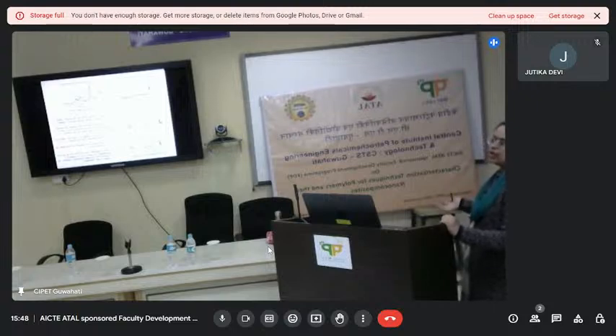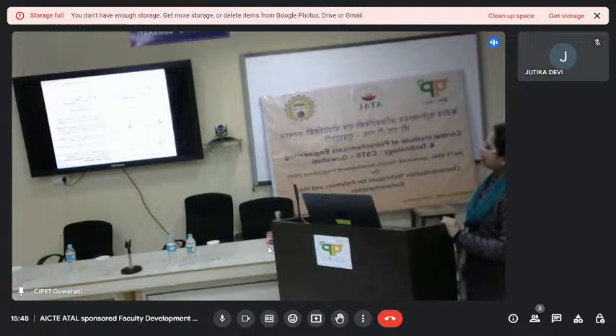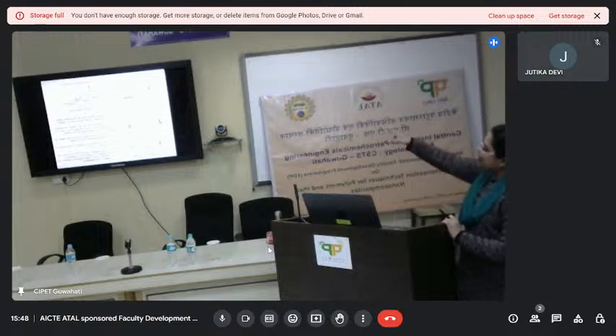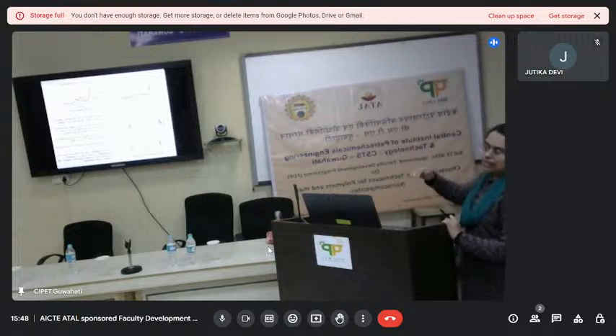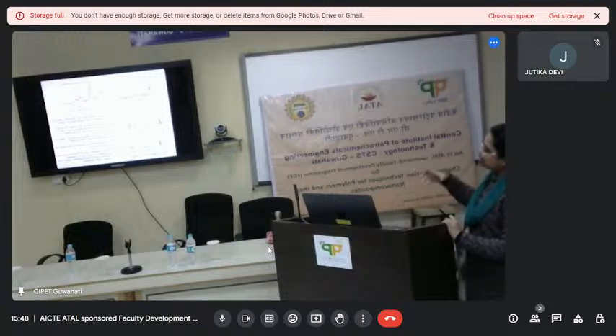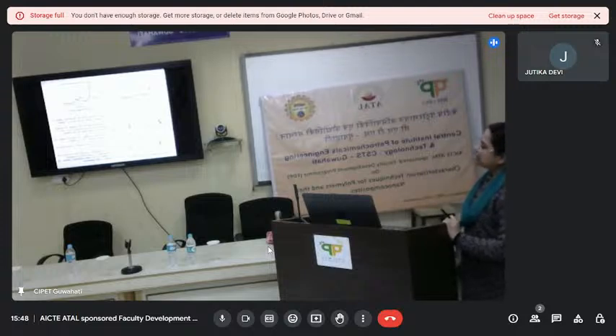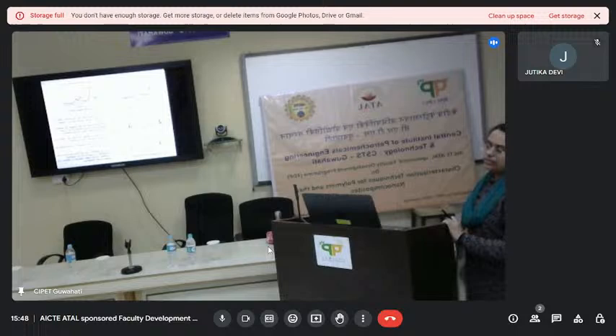So when there is a core shell or composite sample, the planes of both the materials will be visible. And with the deposition of zinc oxide shell over zinc sulfide core, the dominant 111 peak of zinc oxide gets suppressed, and it's that more intense 111 peak which is shown there on the right hand side. When the shell was deposited, that peak got suppressed or became lesser in intensity, and that intensity decrease was more intensified when the amount of shell precursor was increased, or concentration of shell was increased.